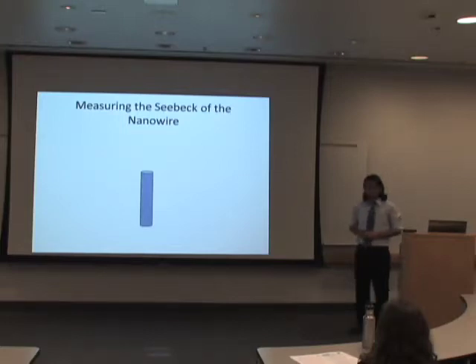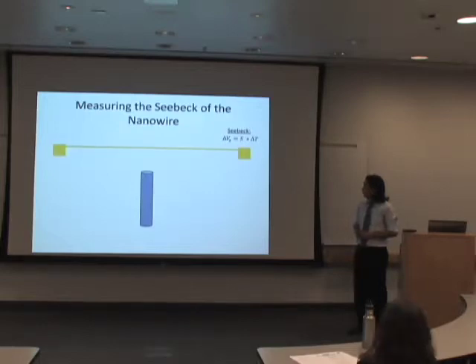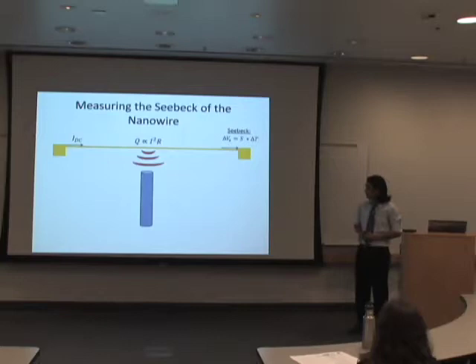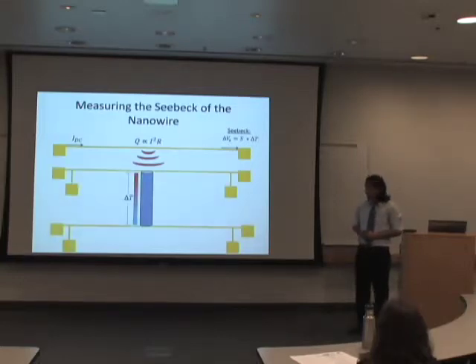So this is how we're actually going to do it. We're starting with the nanowire, and we have the Seebeck equation, and this is the line, which will be the heater line or the heat source. As we run current through this line, this will create Joule heating proportional to the current squared times resistance. This will create the temperature gradient across the nanowire, and now these two lines will be used as thermometers, like I said before, to measure this temperature gradient.